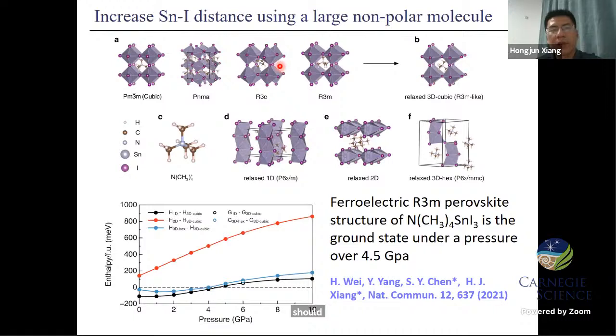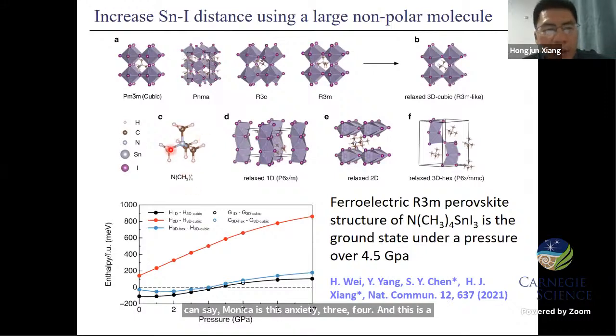Then how to realize this kind of phenomenon? We find this may occur in this kind of material. So we consider a molecule, N(CH3)4, and this is a large non-polar molecule. And we put this molecule at the A site of the perovskite, for the three-dimensional system. The B site is tin, and the X site is iodine. And then we found that the ground state is the ferroelectric R3m-like structure.